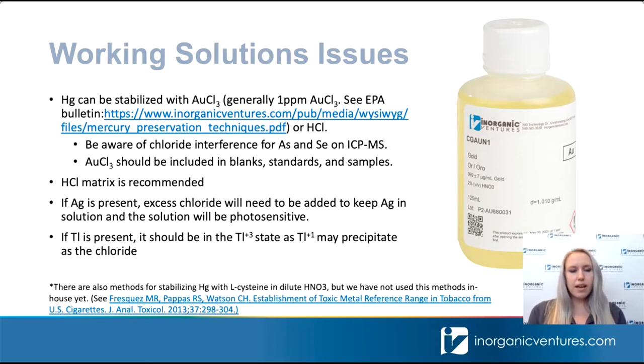Another element that may have issues is thallium. So if thallium is combined with hydrochloric acid, it does need to be in the +3 oxidation state. Thallium in the +1 state will precipitate with chloride. So if you're ordering standards from us and you're going to be mixing a thallium standard with any form of HCl, make sure that you let us know during the quoting process so that we can add a note to use thallium 3+ to prevent precipitation with hydrochloric acid.